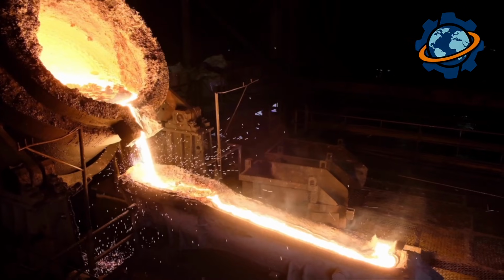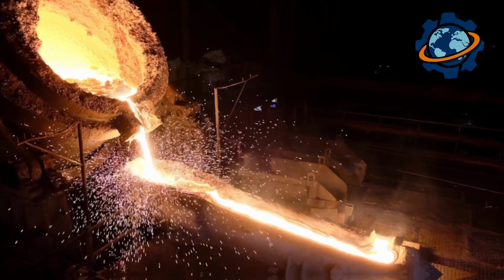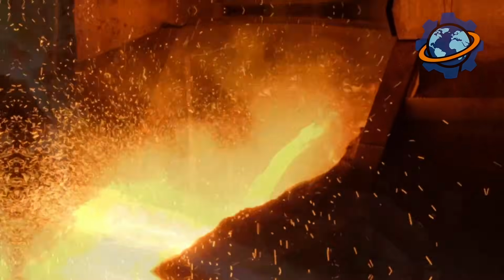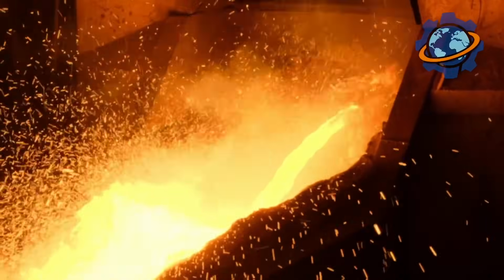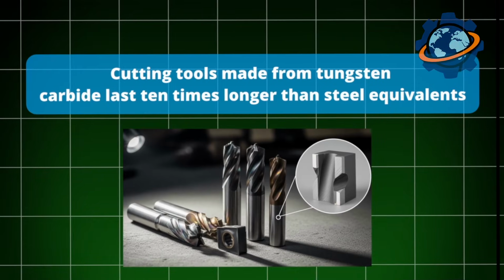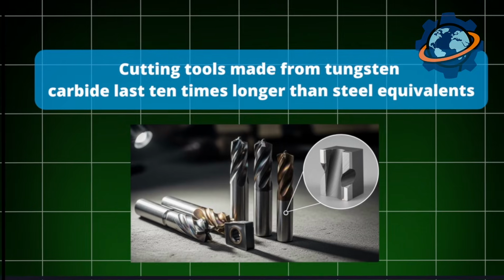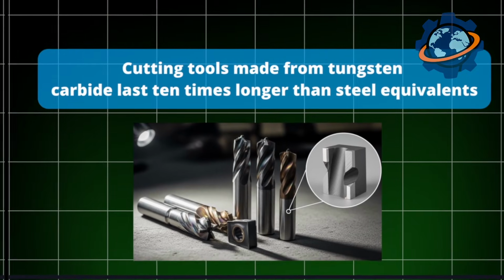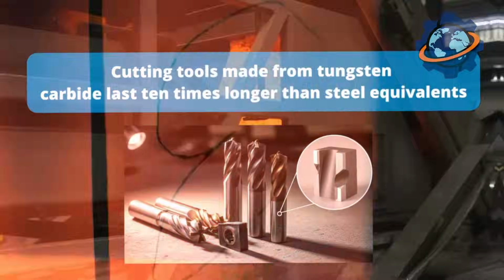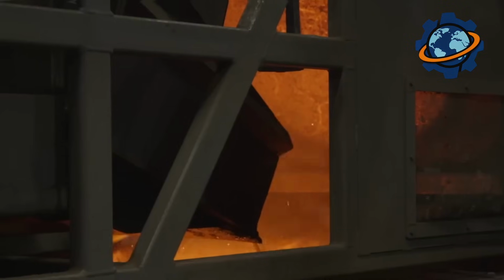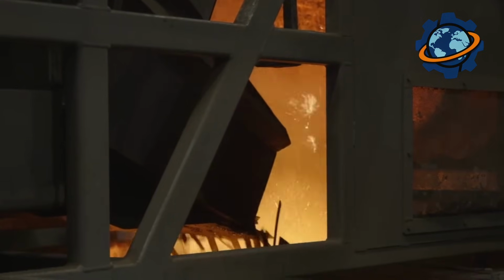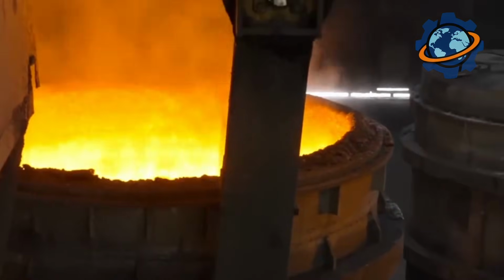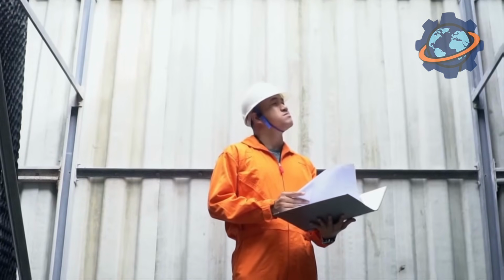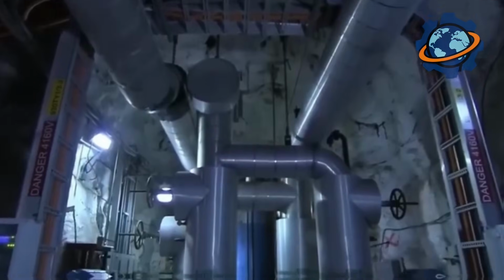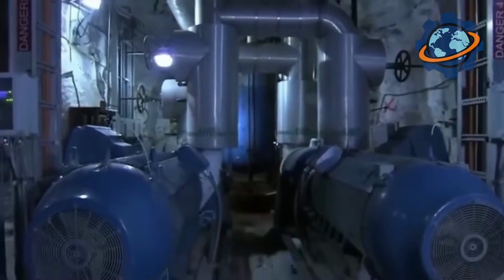The most common tungsten product worldwide is tungsten carbide, tungsten powder mixed with carbon, sintered together. Tungsten carbide achieves hardness second only to diamond. Cutting tools made from tungsten carbide last 10 times longer than steel equivalents. Mining drill bits, machining inserts, industrial dies. Anywhere extreme wear occurs, tungsten carbide dominates. The material cuts steel like butter but shatters under impact. Drop a tungsten carbide block on concrete and it explodes into fragments. The combination of extreme hardness and extreme brittleness defines tungsten's paradox.